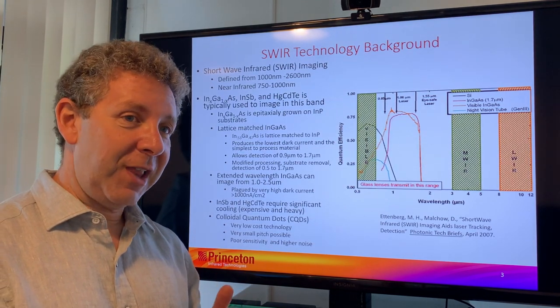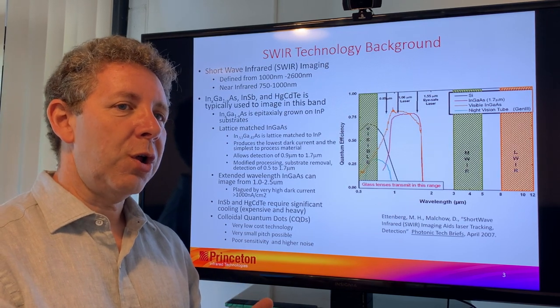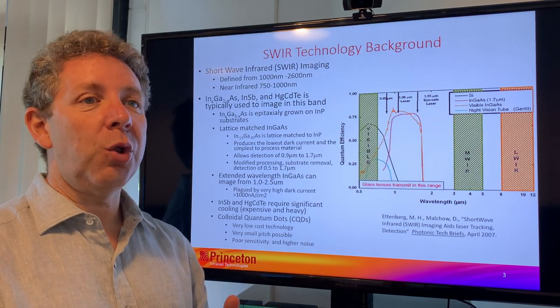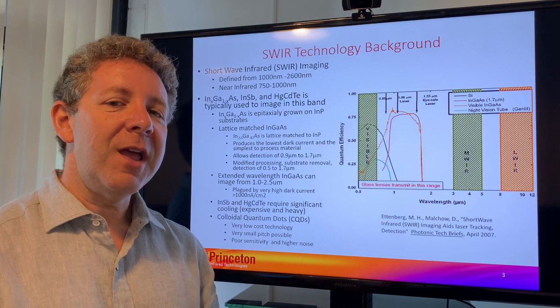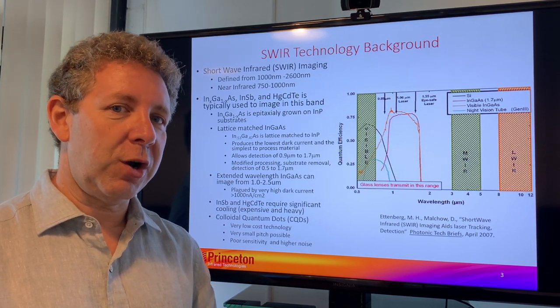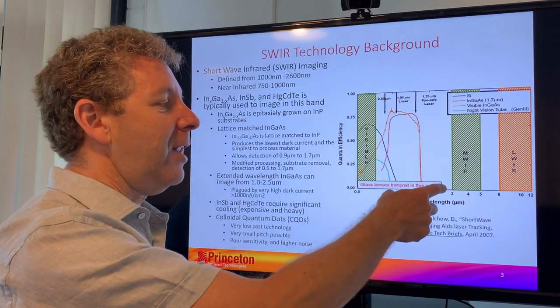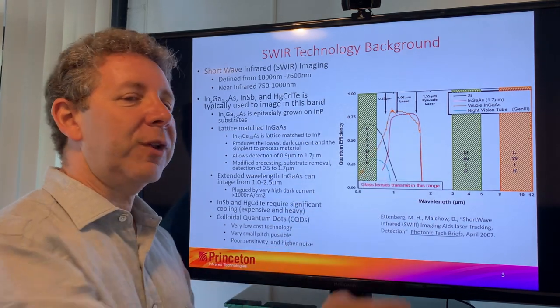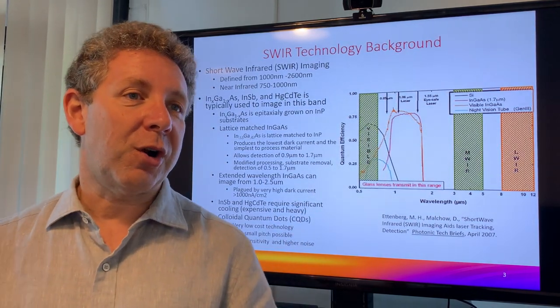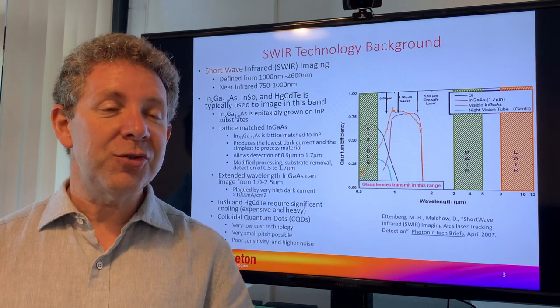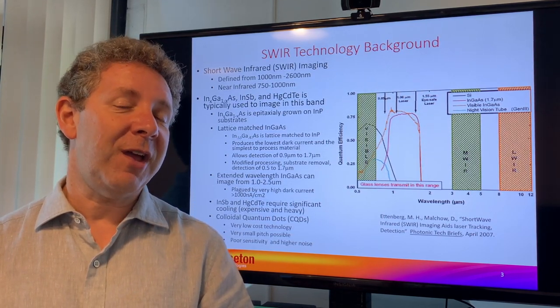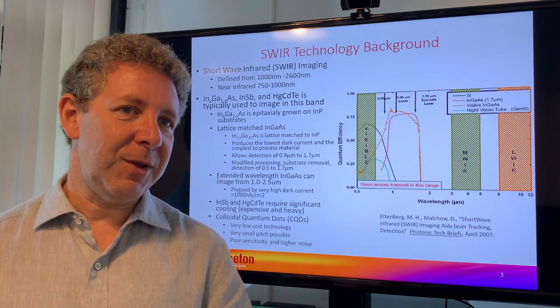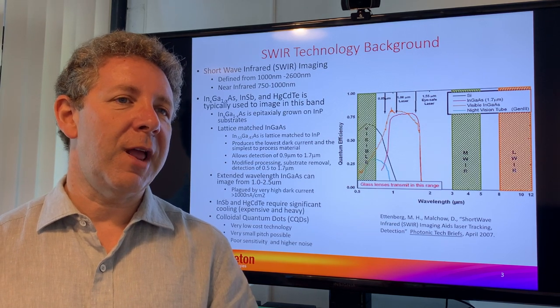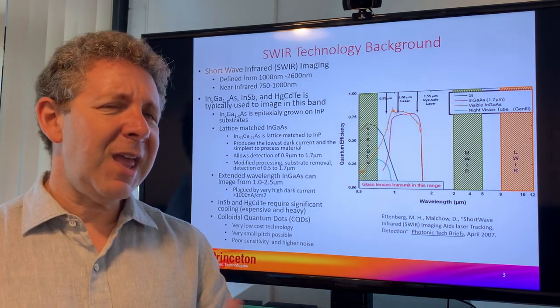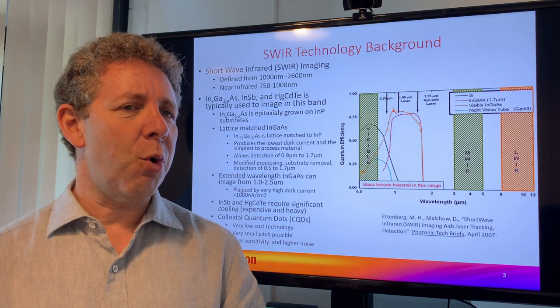When we shift the lattice constant to go to longer wavelength material, we're no longer lattice matched to indium phosphide, and that causes huge amounts of dark current in our material. So you can make InGaAs that goes all the way up to 2.6, but it has a lot more dark current and is generally not used. People usually use mercury cadmium telluride or indium antimonide because they have lower dark current and more in production. But InGaAs in that wavelength range is starting to become more and more common.